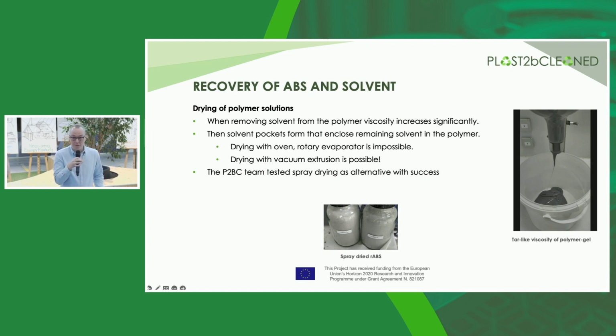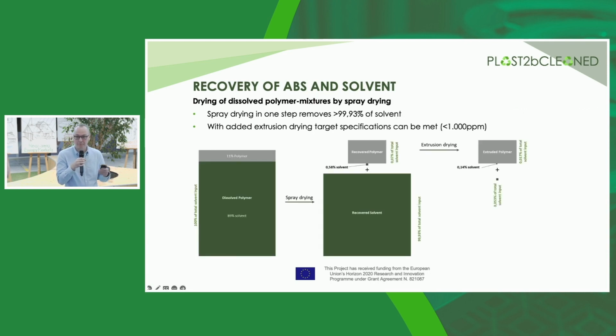What is obviously possible is to use a vacuum extrusion. Here you have high shearing forces, quite high temperature with a vacuum. So this is one possibility, but for Plast2bCleaned we pursued another approach using spray drying. And we tested this with success. On the bottom side you can see some spray dried material. And the next slide shows you that